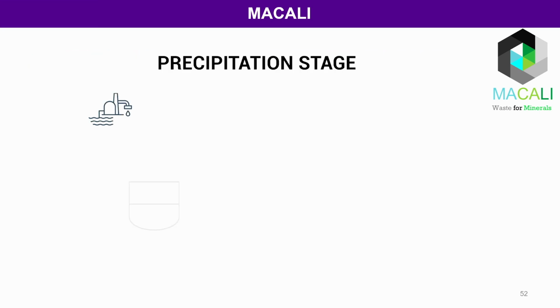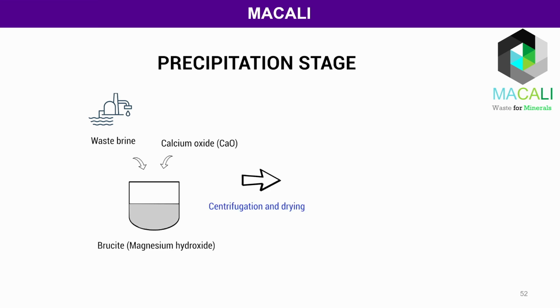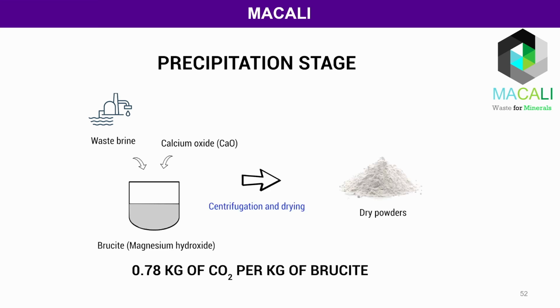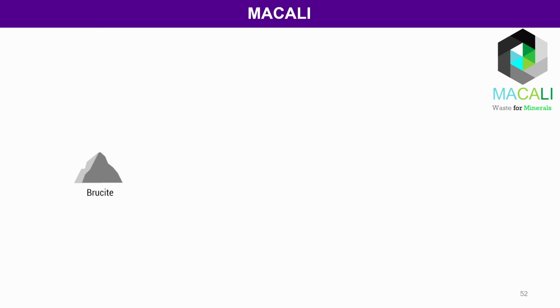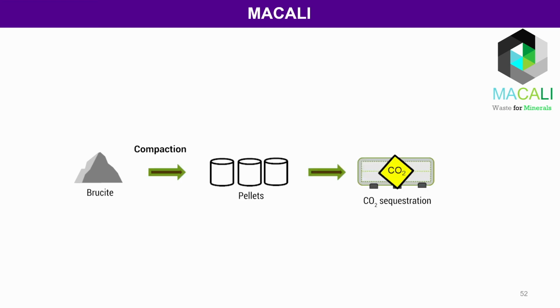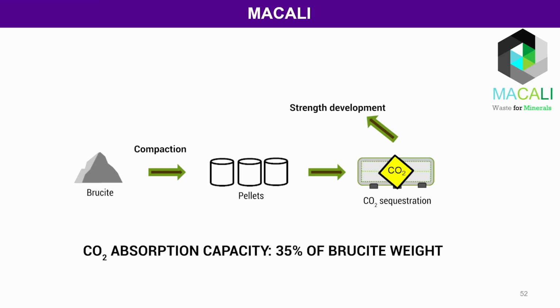Our brucite production process reports around 0.78 kilograms of carbon dioxide emissions per kilogram of brucite. What is unique about the precipitated brucite is that it sequesters carbon dioxide for strength gain. Its carbon dioxide absorption capacity can reach up to 35% of brucite weight.